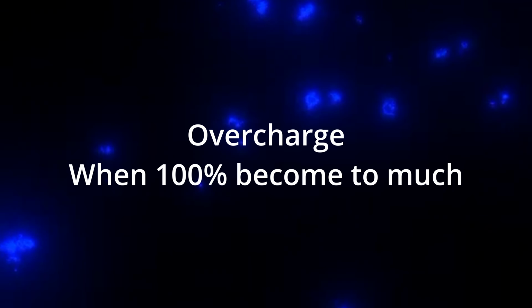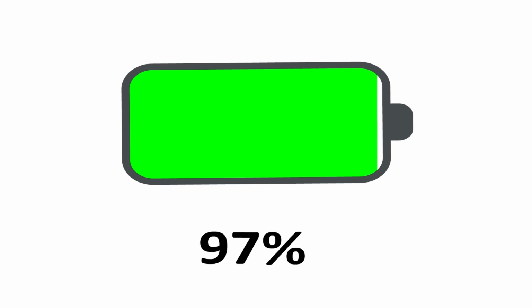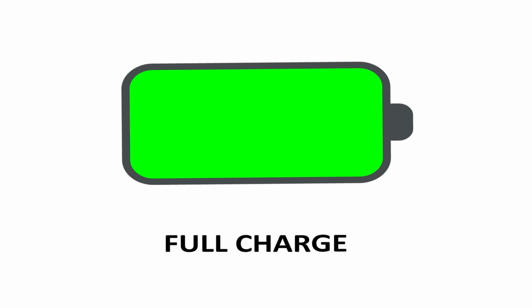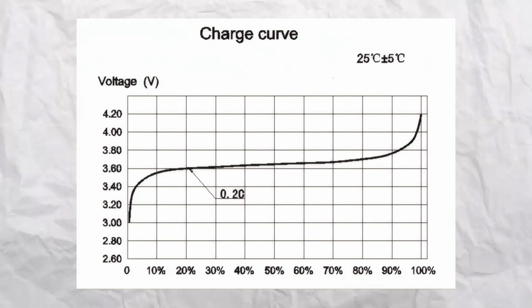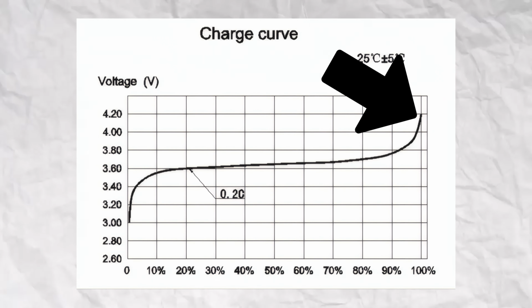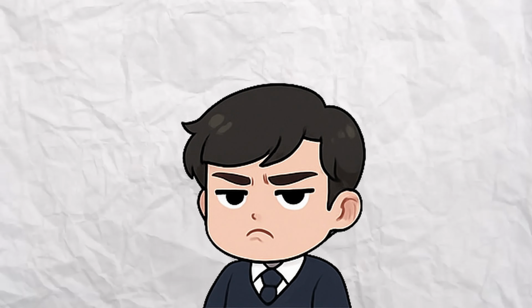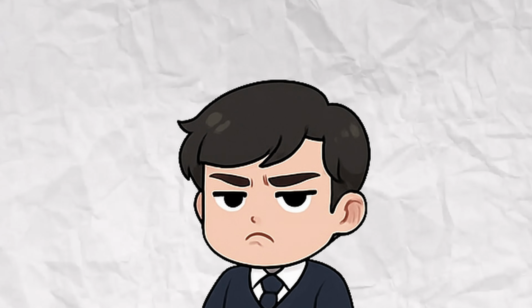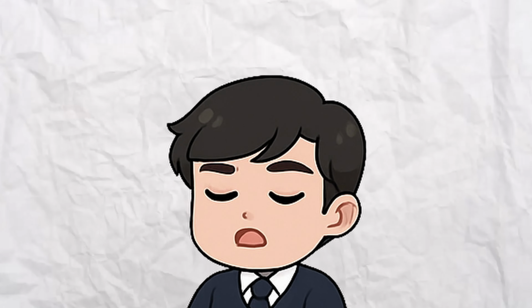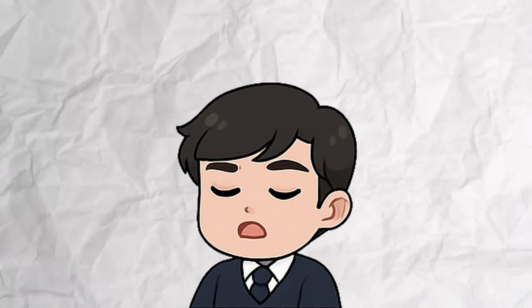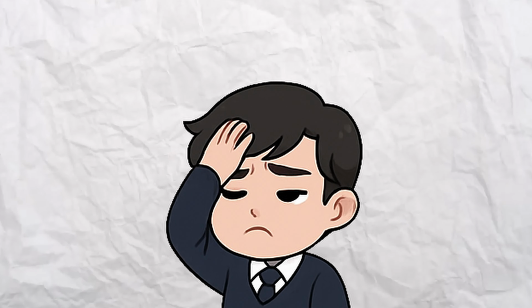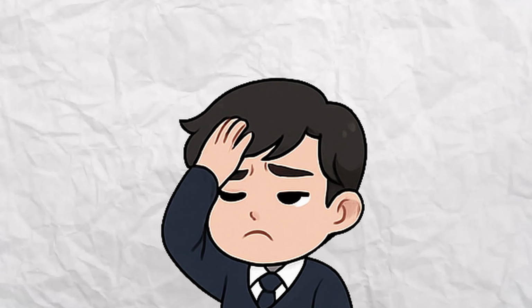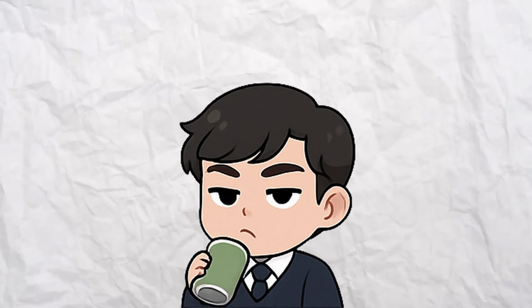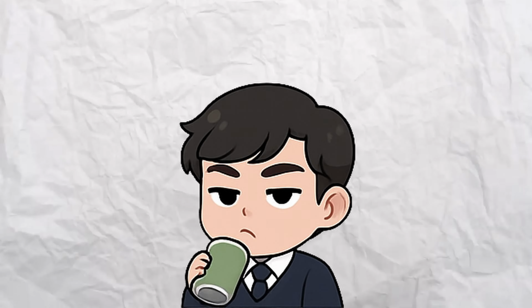Overcharge, when 100% becomes too much. On the other side, keeping your phone fully charged for too long is just as bad. At 100%, the cathode is under extreme stress, sitting at around 4.2 to 4.4 volts. At this voltage, oxygen atoms start escaping, the electrolyte oxidizes, forming gases and unstable compounds. The SEI layer on the anode also keeps growing, consuming more lithium and increasing the resistance. This makes the battery less efficient and generates extra heat, a perfect recipe for faster degradation.